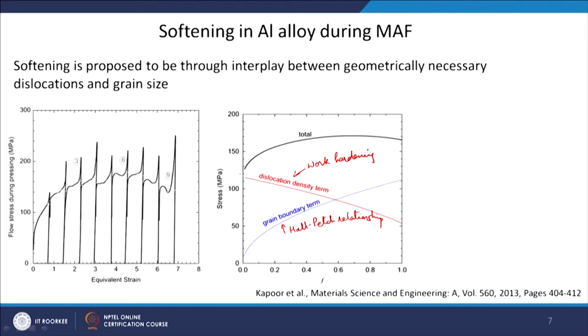So, that contribution is increasing, and the dislocation density term is decreasing. When both are contributing, initially there is an increase in the flow stress, but later on, when the dislocation term is coming down and there is not much contribution from the refinement in grain size, softening takes place. Of course, in some other cases when the grain size is very fine, people have attributed this softening behavior to a change in the deformation mechanisms. Earlier we discussed grain boundary sliding. So sometimes the softening can be due to a change in deformation mechanism, or it may be due to microstructural effects, that is, how dislocation density and grain size are changing and affecting the overall stress.